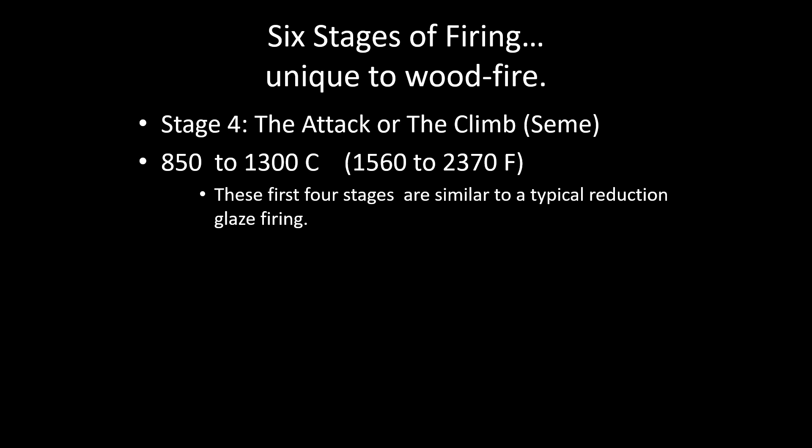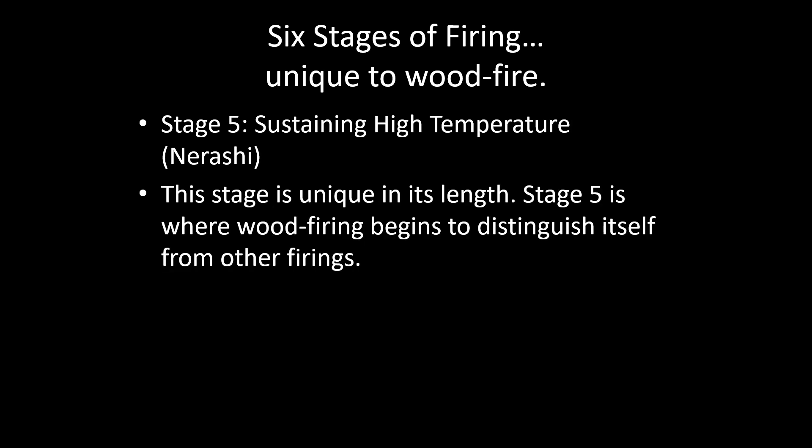These first four stages are just like what you would do in a reduction glaze firing. If you were to stop the firing right now, the glazes would be fully melted and you would have a great firing. But if you're firing for ash effect, then you need to keep going. That gets us to the fifth stage — the sustaining of high temperature, the nerashi. This stage is unique because its length is going to determine the quality of effects you end up with. This is where wood firing really becomes wood firing and distinguishes itself from other firings.